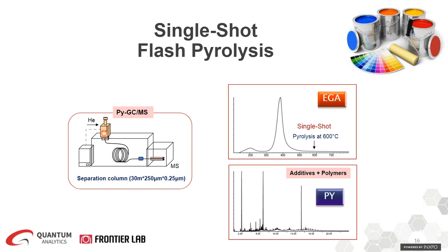And so if you follow that sort of use, then periodically, maybe once a quarter would be typical. And it will, of course, depend somewhat on the number of samples run. The maintenance procedure is to remove the quartz tube and either replace or flame clean, and then there is a ferrule and a needle that you replace. Those are the only consumable items. Once that is put back together, you have a brand new pathway from the point that the sample drops into the system up to the point that the pyrolysates or other analytes enter into the GC inlet. The GC inlet remains typically very clean in this technique because the residual materials are retained in the cup and are removed. So those would be the maintenance procedures that you would have on top of your normal expected GCMS procedures.